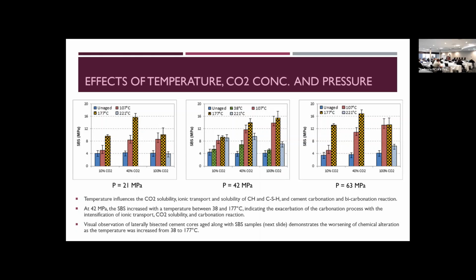Time was not on our side on this project, but I can give you some good news. With my new testing procedure with relatively larger samples, like 1.25 inch diameter, we do have some samples almost 6 months old that we're going to test, and we hope to get more samples now at different temperatures. Most of my samples are limited to about 85, 90 degrees C because they are atmospheric. But we hope to get some samples that can go to 200 C under pressure. So we are still getting there, but it's very tedious time and work.